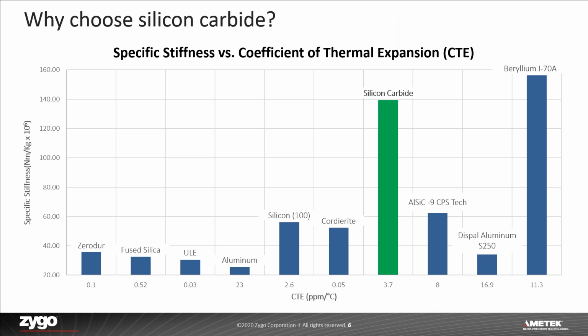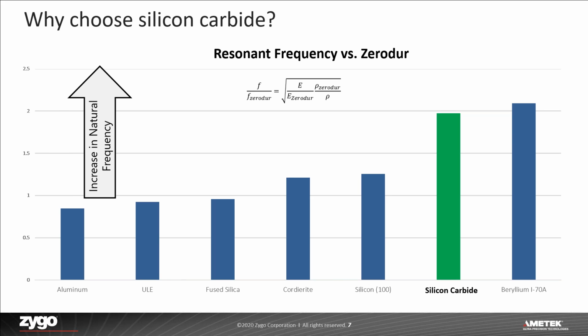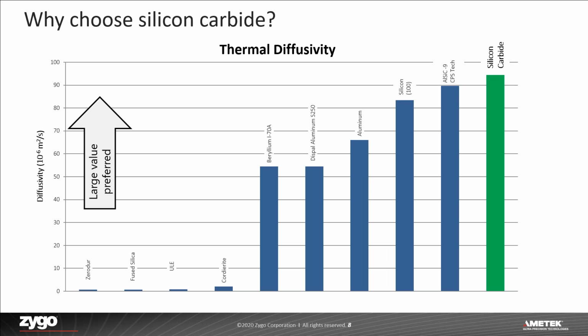As it relates to the coefficient of thermal expansion, silicon carbide combines that high specific stiffness with a low CTE in comparison to other materials. HEL optics undergoing acceleration strongly benefit when a material is selected that has a high resonant frequency, and silicon carbide has the highest value out of the non-toxic materials. And high thermal diffusivity is desirable so that heat absorption does not affect the beam path.